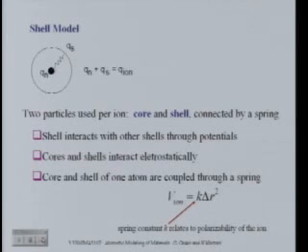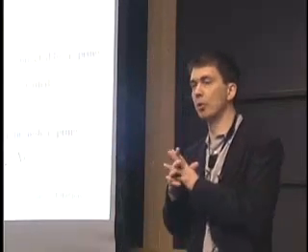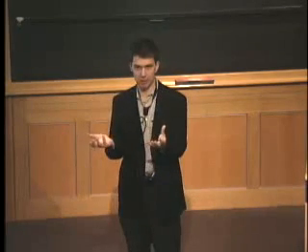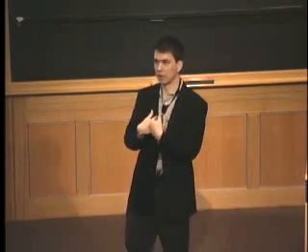An essential piece that was added in the late 60s, early 70s was polarization. An important thing in oxides is that you have strong electrostatic fields, so when you put an electron density in a field, it can polarize. This is particularly important for the oxygen ion. If you put the oxygen ion in a non-symmetric position, one where the field doesn't vanish, then, since an oxygen ion is highly negatively charged and has a lot of electrons, the electron density cloud will polarize, and the oxygen will actually carry a dipole.